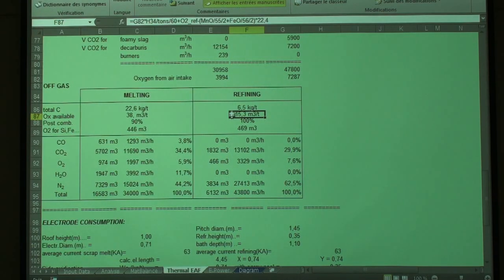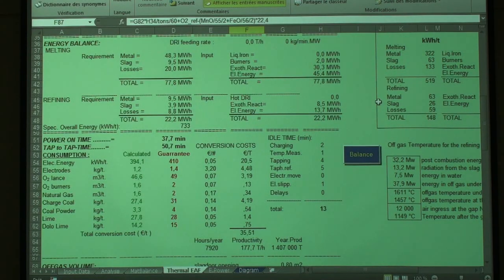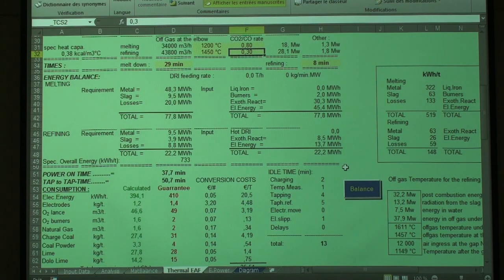Oxygen available. Post-combustion, you have even more because of the remaining 7.6%. That's why you can burn all the CO, which doesn't mean that the CO will be burned into CO2 in the bath. So in the bath, for the thermal balance, we just consider 0.3. The rest of the post-combustion is done above the bath. That's why the energy from post-combustion was taken into consideration, right?